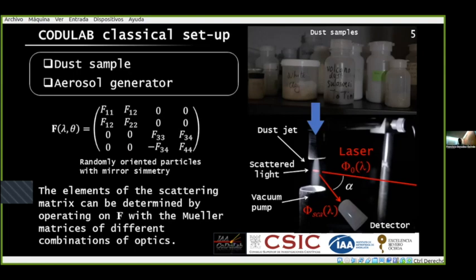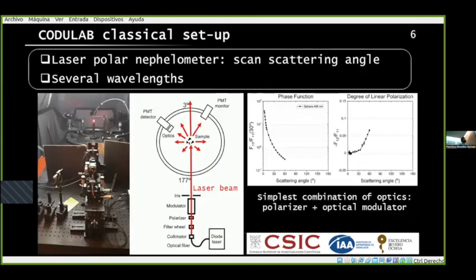Because it's a cloud of randomly oriented particles, and we assume that they have mirror symmetry, the scattering matrix simplifies greatly and only has this block diagonal non-zero elements. Actually, only six of them are different. And we can determine them by introducing in the setup different combinations of polarizers, both at the source and at the detector. So by doing different combinations, we can measure all these elements. And then we do that as a function of scattering angle so that we can build these nice curves of intensity or the phase function and the degree of linear polarization.